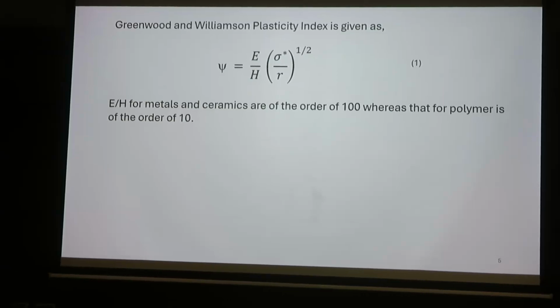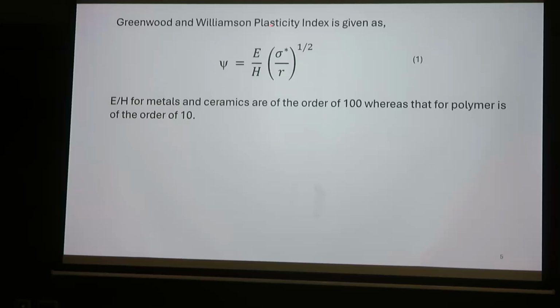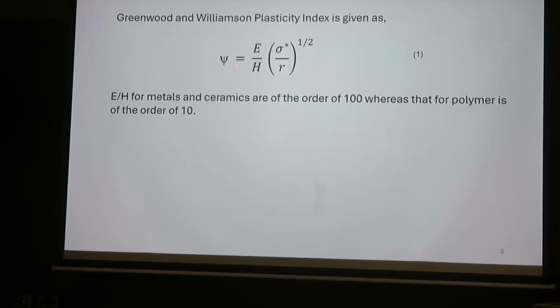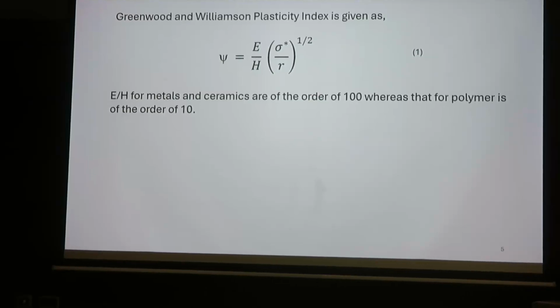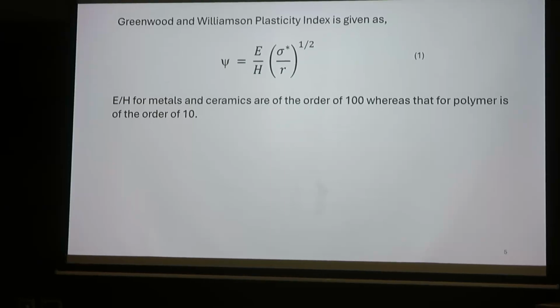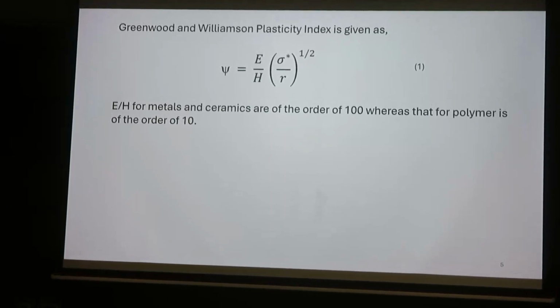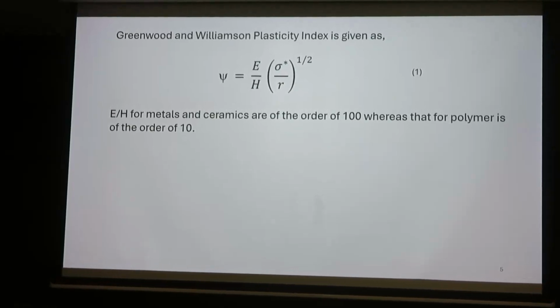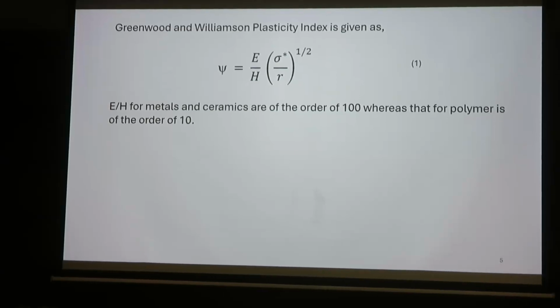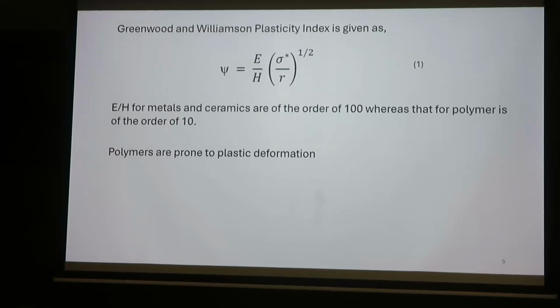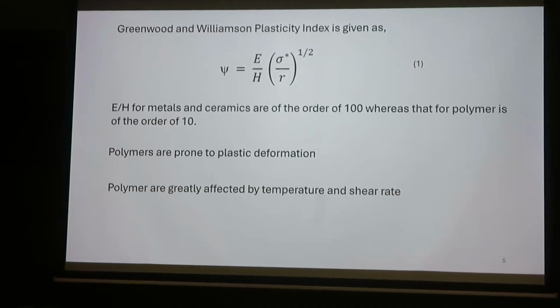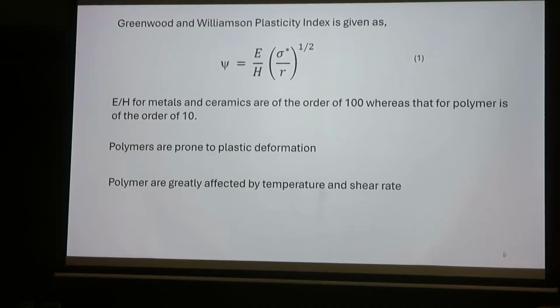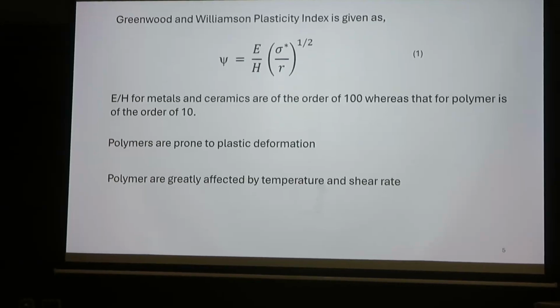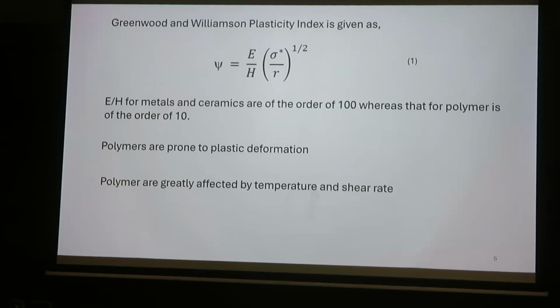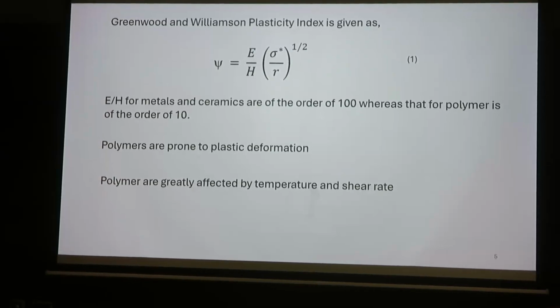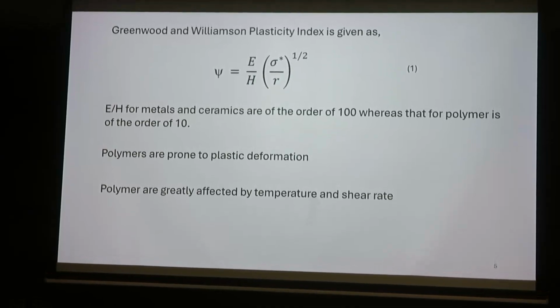For polymers, you might have seen this Greenwood-Williamson plasticity index, and here the ratio E over H for metals and ceramics is on the order of hundreds, whereas for polymers it is on the order of 10. What it means is that polymers can deform plastically much more easily compared to metals and ceramics. Polymers are very prone to plastic deformation, and they are greatly affected by temperature and shear rate. This is another important thing to note. Obviously, temperature has a very great effect, but also shear rate, how fast we are deforming the material. So that's why you see there is a lot of speed dependence on tribological performance.